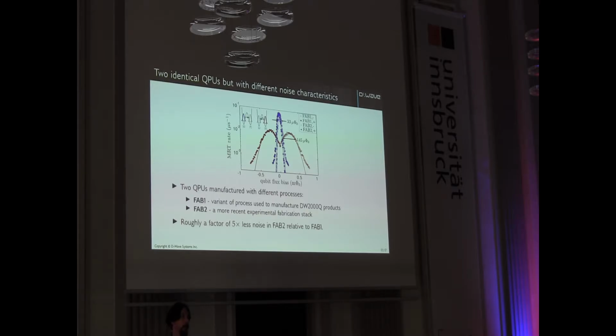You have to have a model for what that noise spectral density shape looks like, but you can then calibrate against it. What I want you to take away from this is comparing the widths of the Fab1 and Fab2. You can see there's about a factor of 5 difference between those two processors. So just keep that in mind. It's about a factor of 5 difference in what's looking like the decoherence processes, or those energy exchange processes.